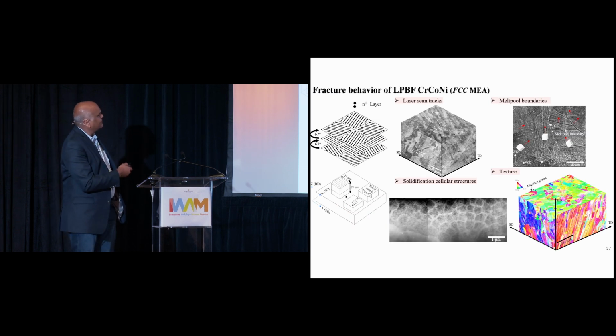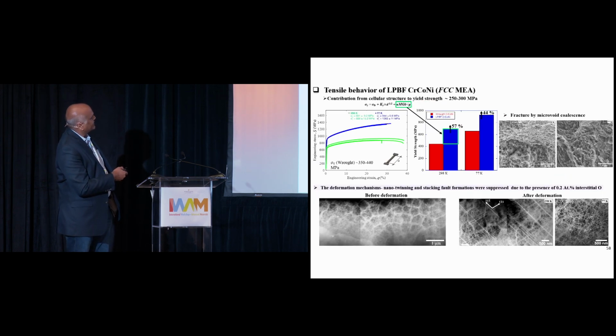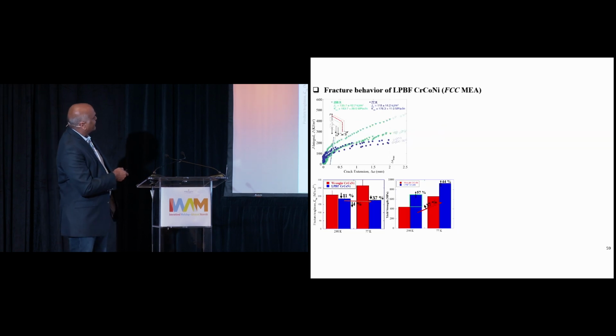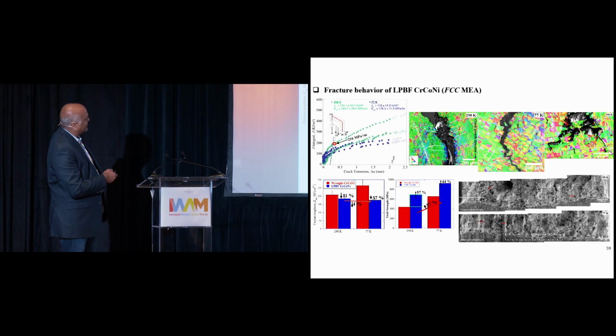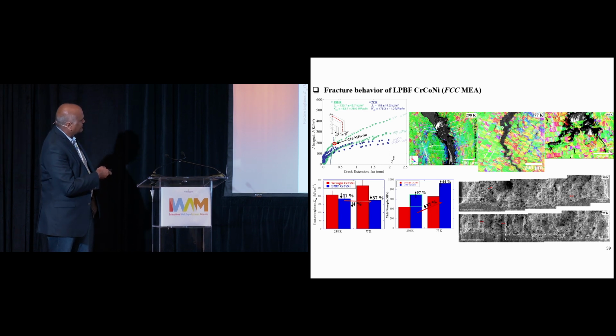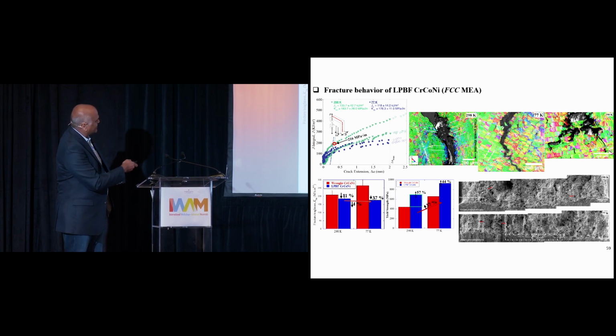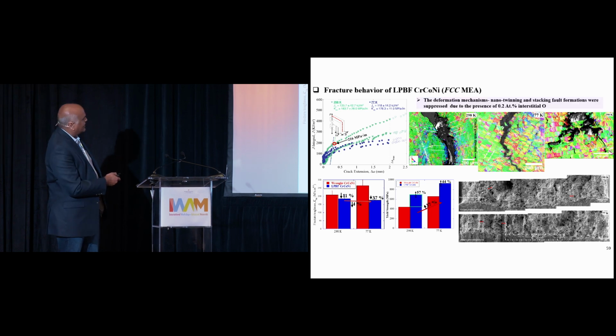When you 3D print these metals, the strength goes up. This is a cobalt-chromium-nickel alloy with equal amounts. The strength goes up whether you test at 298 or 77 Kelvin, and this happens because you have twinning and other mechanisms coming into play. But what's interesting is if you 3D print this alloy, you get the high strength, but fracture toughness seems to slightly reduce—the blue shows a slight reduction compared to the wrought alloy.